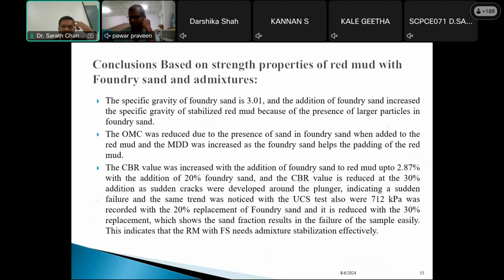The conclusion based on the strength properties of red mud with foundry sand and admixtures. Basically, the CBR value increased with the addition of foundry sand to red mud, up to 2.87% with the addition of 20% foundry sand. The CBR value reduced at the 30% addition as sudden cracks developed. Yes, actually, when we used 30% of foundry sand, when we were doing the CBR test, we observed sudden cracks in both CBR and UCS.